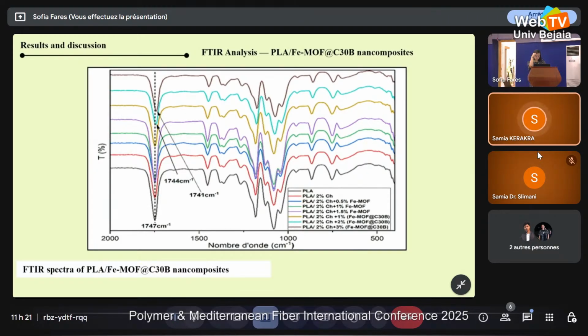Just slight shifts of the carbonyl stretching band from 1744 or 47 to 1741 were observed in the 2 and 3% composite formulations, and this shift suggests weak interactions between the PLA matrix and pillars, likely through hydrogen bondings or similar interactions, like van der Waals interactions.